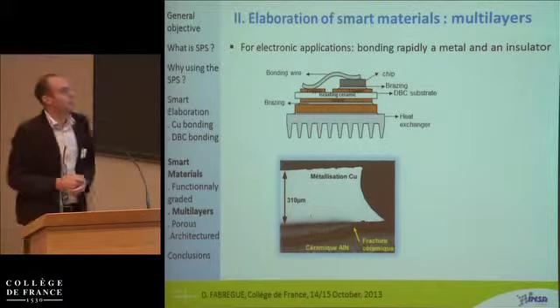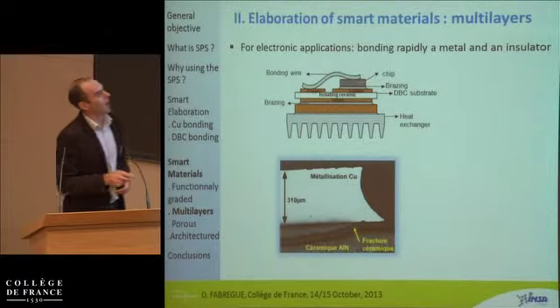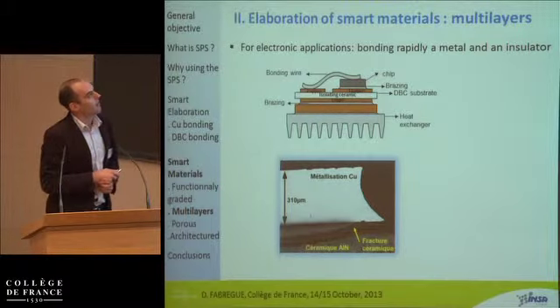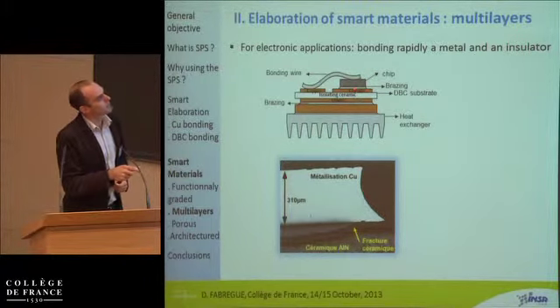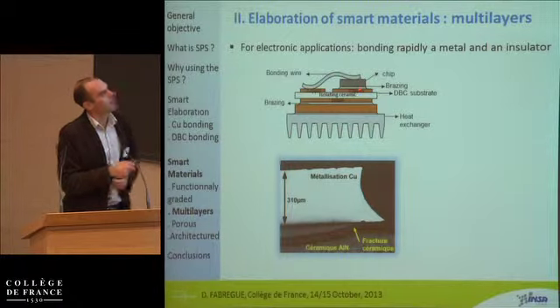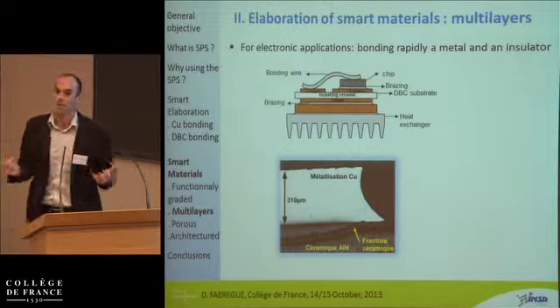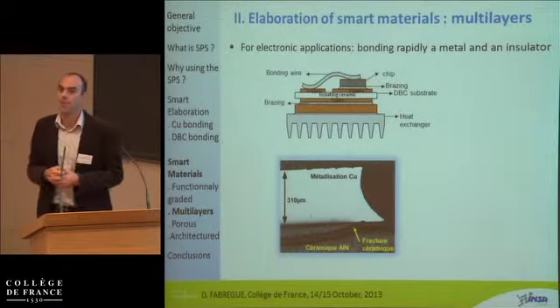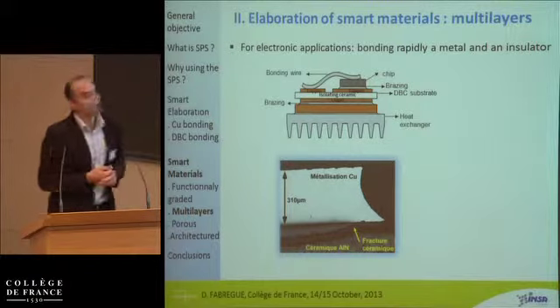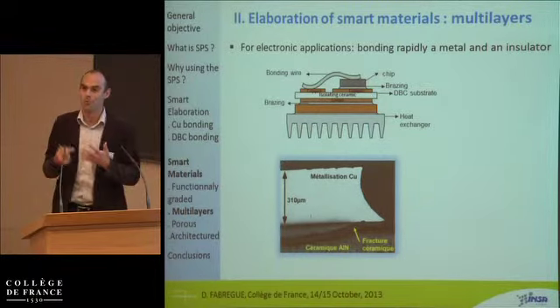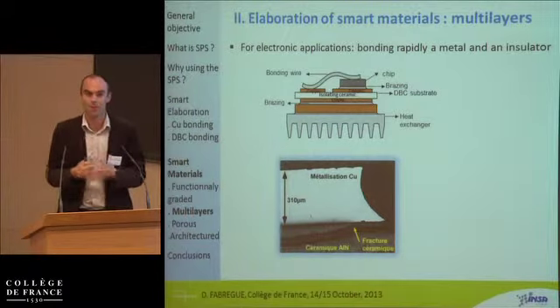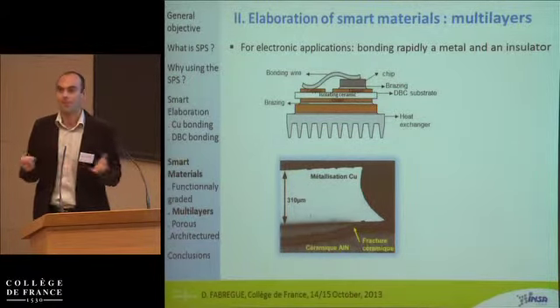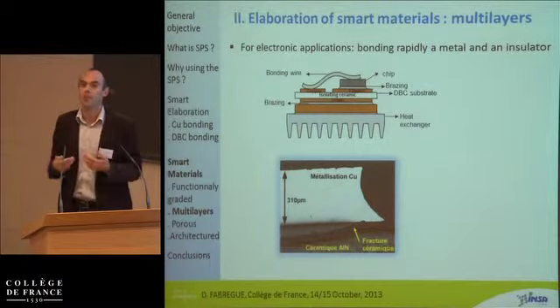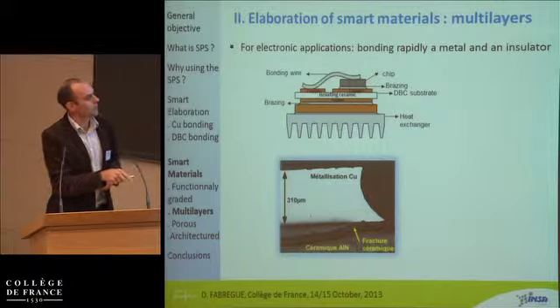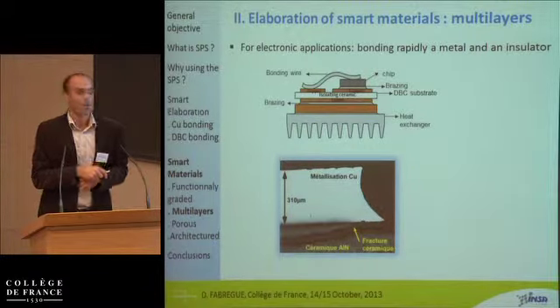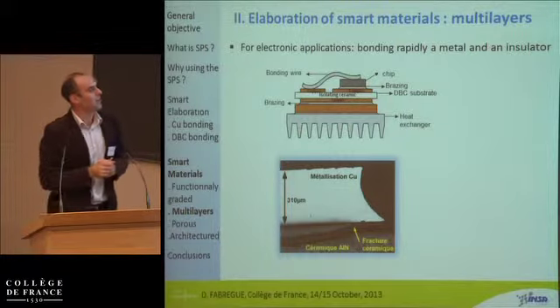Let's go back to microelectronic applications now. So I already talked about this part here. There's another one which is quite interesting: these people are trying to couple copper, which is a metal, with insulating ceramics, and this ceramic is usually aluminum nitride. The big problem, if you succeed in coupling these two materials, is that the thermal expansion coefficients of these two materials are very different. So if you have thermal cycles, then you have thermal fatigue, and then you have fracture that occurs in the aluminum nitride. This is something that these people don't really like, as you can imagine.